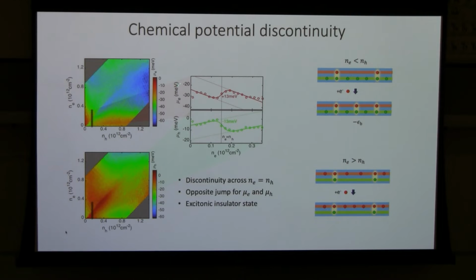What you can see is that the chemical potential of the electrons has a general dependence on electron density due to the electron-electron interactions. But then there is a jump of chemical potential when the electron and the hole density equal each other. This jump is about 10 to 13 milli-electron volts. When you look at the chemical potential of the holes, it has the same magnitude but the opposite sign. This chemical potential jump, we think, is related to the exciton binding energy.